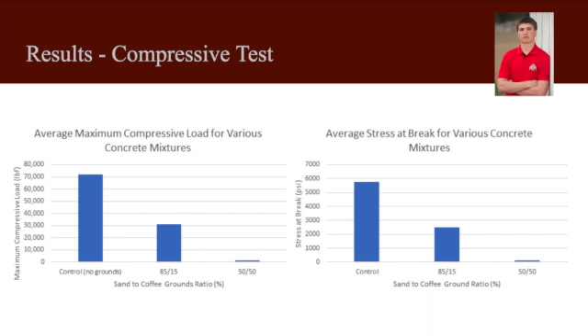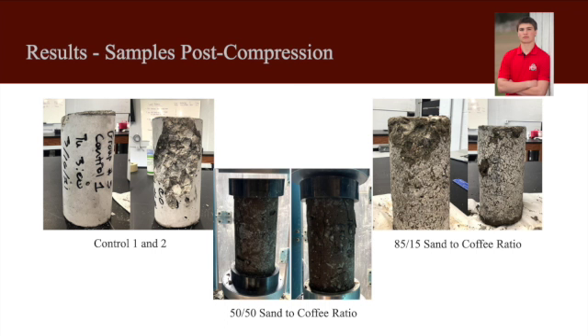For the average stress at break, which is essentially the stress at the failure of the cylinder, it showed very similar properties to that of the maximum compressive load. Once again, as more coffee grounds were added to the mix, the strength of the concrete cylinders decreased drastically. Here are the cylinders post-compression tests.